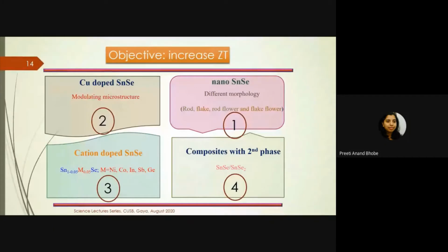So our objective was somehow to increase the ZT. We took 4 different approaches for this. We prepared nano, because we know that once you have a nano form of any material, there is a lot of control one can have on the different physical properties of such materials. In the second strategy, we tried to put in copper, because copper is known to be a good electrical conductor. So we thought maybe a small amount of copper would help us in improving the ZT. But what we found was modulation of crystal structures, and also the other 2 approaches.